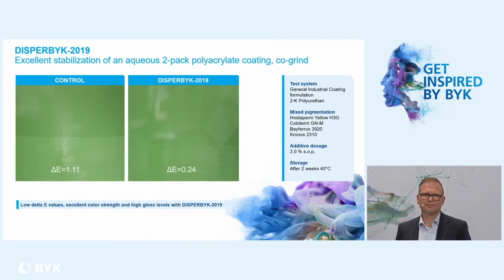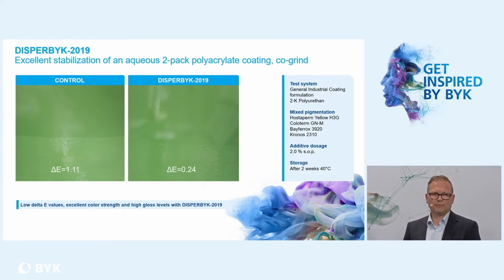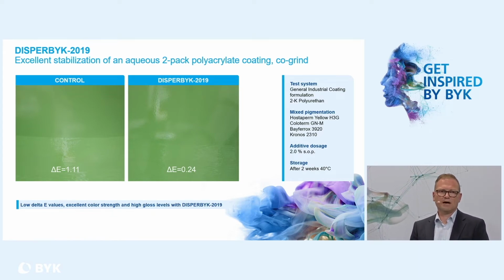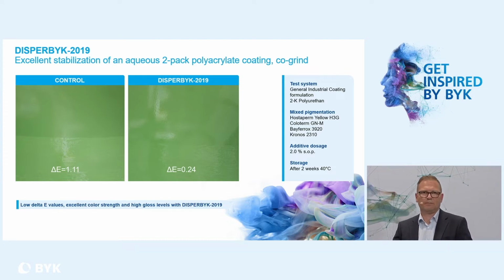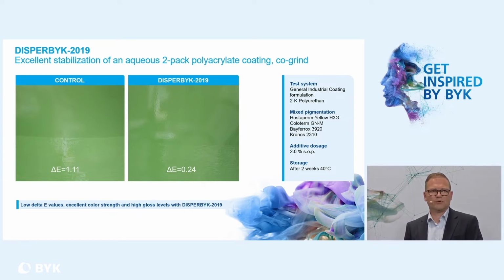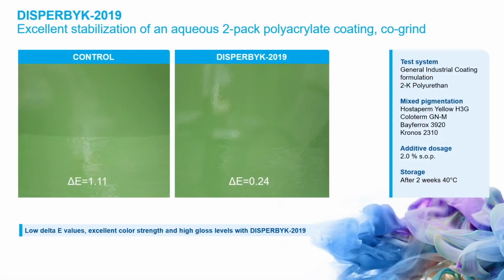Another example, industrial coatings. Here we see a 2-pack PU coating for industrial application, mixed pigmentation, yellow pigment, green pigment, again an inorganic yellow pigment, and titanium dioxide. And after storage of 2 weeks at 40 degrees, we applied the paint. And you see the lower delta E value with DISPERBYK-2019. Just a delta E value of 0.24, which is very, very good, combined with a high gloss and good color strength development. So it means both additives are very universal in use.